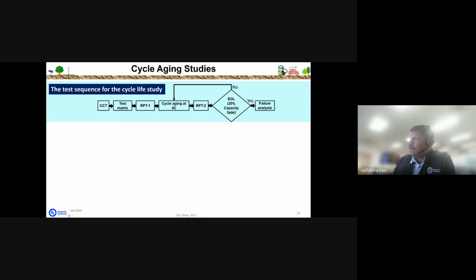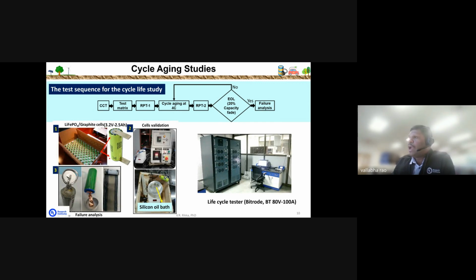And then after it reaches the end of life, we can go for the failure analysis. Once you identify the main failure aging mechanism, that can help us to mitigate the aging mechanisms over the long cycles. So for this experiment we have procured 100 commercial lithium cells, and initially we have done the cell validation. We can say that cell validation comes under the category of reference performance test.